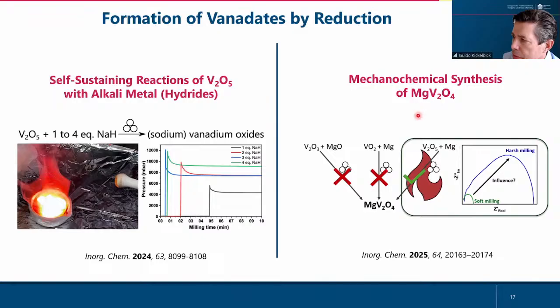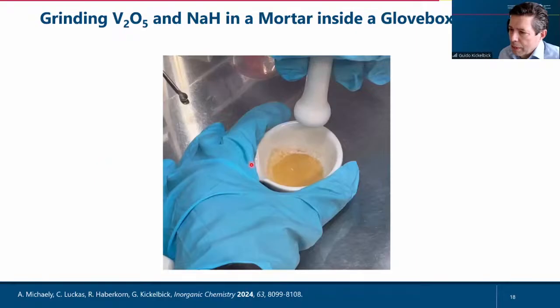I will not present you this magnesium vanadates today. I just want to give you a short glimpse on these vanadium oxides. So what we wanted to do here is not using lithium hydride, but sodium hydride together with vanadium oxides, vanadium 5 oxide. And this is an experiment a bachelor student of mine was doing during his bachelor's thesis. And this was really strange. What was happening there, and now it's strange that it doesn't start. So let's see whether we can do that in another way.